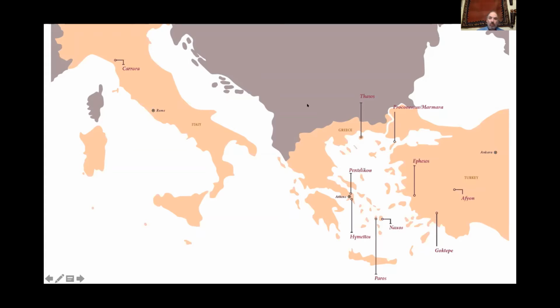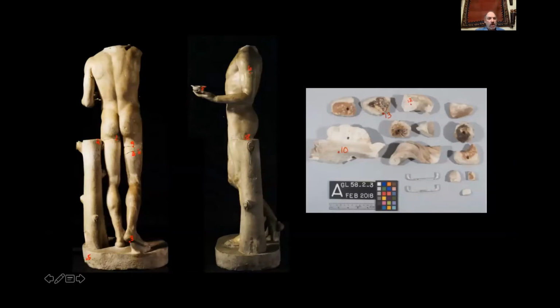These were the major marble producing regions, and the possibility that these different sources could have provided marble for the Bacchus, whether the original pieces or later restoration pieces, was of interest, especially for the restoration process. So during the restoration, Corey and her team, as they were taking apart the statue, were able to collect small samples, which are identified by these number spots. 15 samples in all from various large fragments of the sculpture, as well as some of the smaller plugs that were placed in various holes during previous restoration processes.